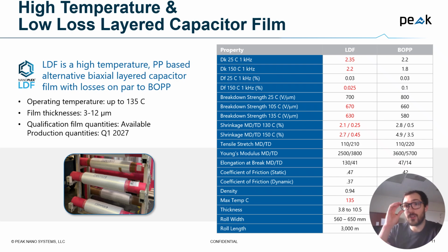But again, there's also this hidden secret on the longevity of the capacitor in terms of heat resistance. When the capacitors run at any temperature above room temperature, BOPP gradually gains a derating factor where its capabilities are reduced from room temperature. And then, of course, just from internal heating, the temperature of the capacitor can easily reach 100C in terms of hot spots, which leads to deratings. Now, this derating isn't usually in the form of lower operational voltages, but it also leads to reductions in lifetime. For example, if you run a BOPP capacitor with a 100C hotspot, not 100C ambient, just a hotspot, so again, high current applications, its operational lifetime reduces by orders of magnitude. You'll see most capacitors with a hotspot of 100C, which is easily reached for, again, the current you need for a high HTS magnet, might be 500 hours if you're lucky. And so, again, this becomes a major constraint on what you can get in terms of your net lifetime.